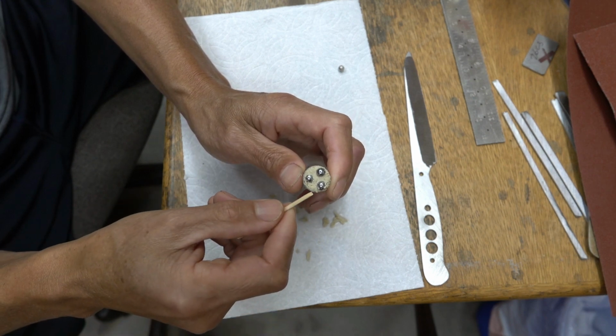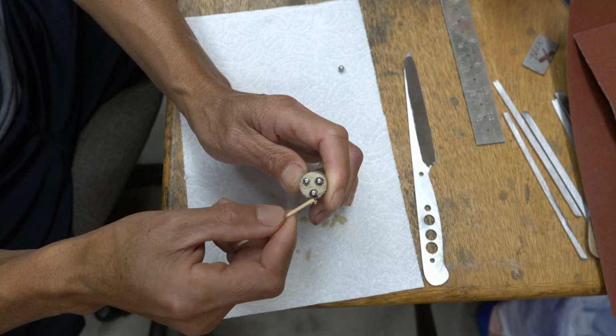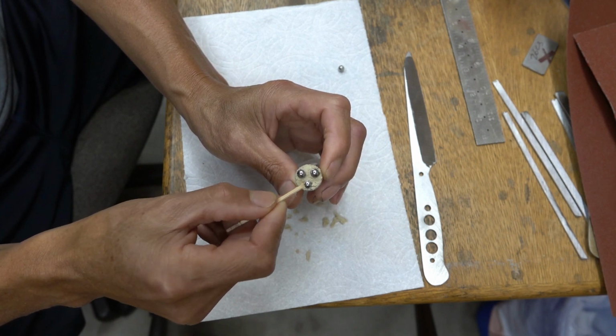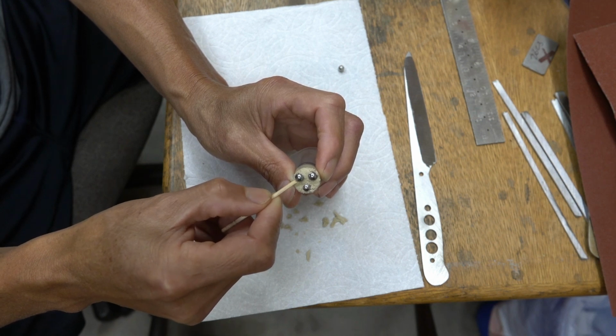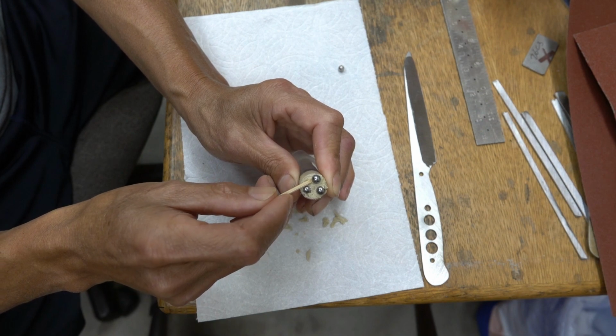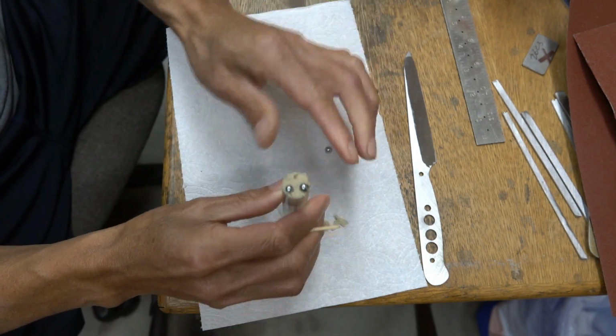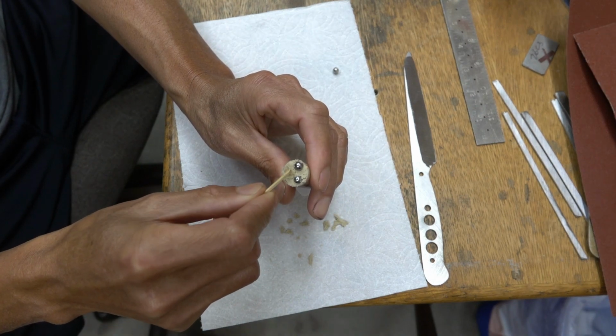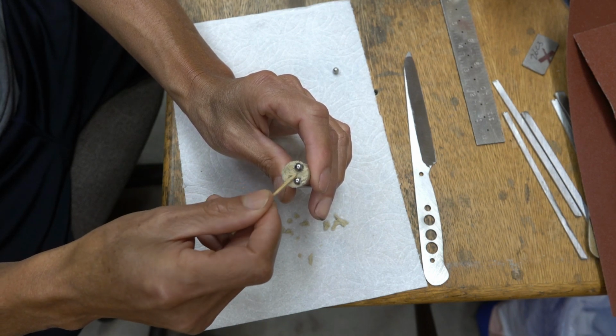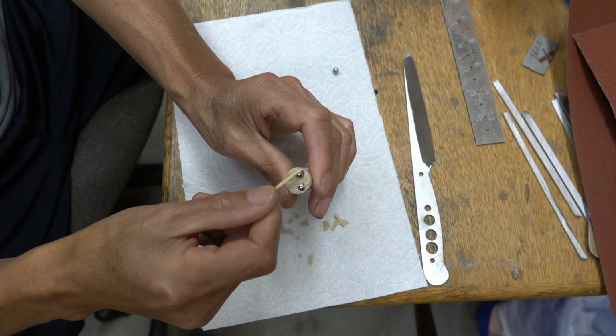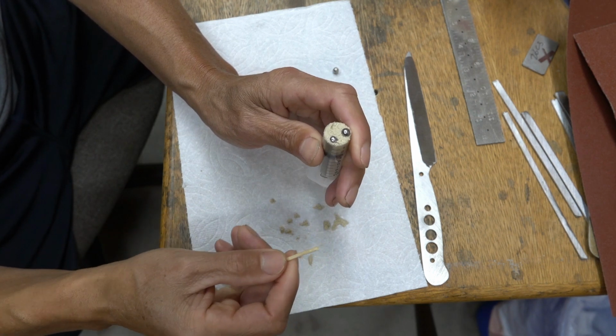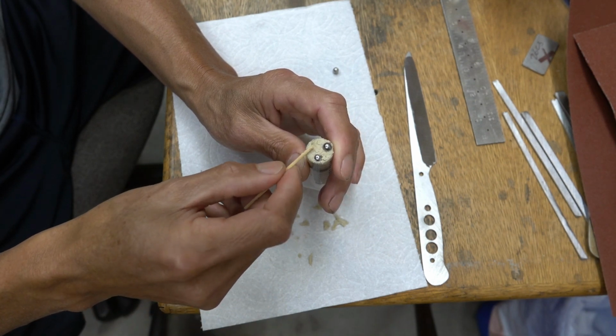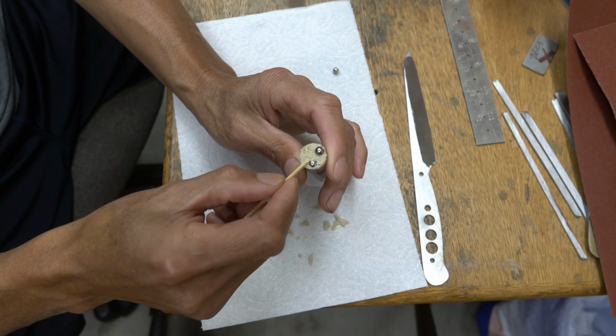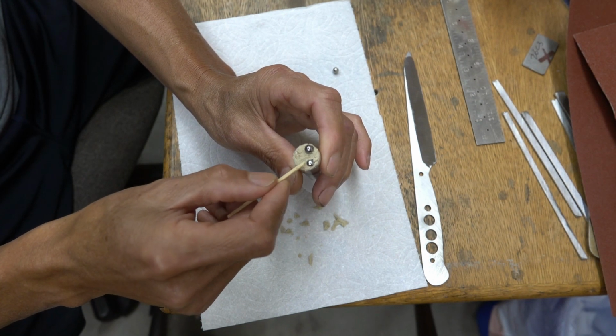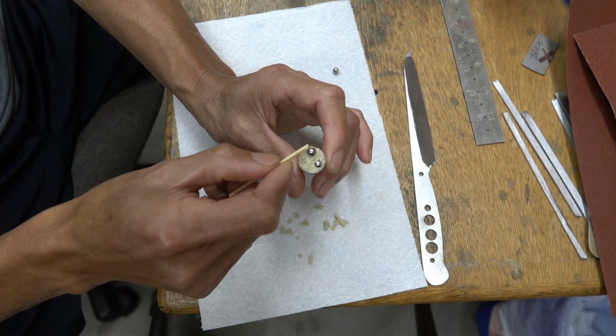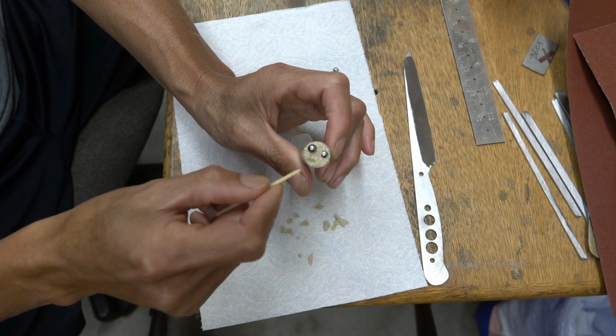And with the weaker matrix, what you're going to see is basically these lower protruding carbides, while the high one, with the weak steel, is going to be gone. It's going to get moved out of there, and they got smoothed over most of the time because of the rubbing part, the lapping part. So overall, at the end of the process, you're going to see that the weaker the matrix, you have a whole lot of low protruding or partial carbides, while the strong matrix that can hold on firmly to the carbide has a lot more protruding, like so.